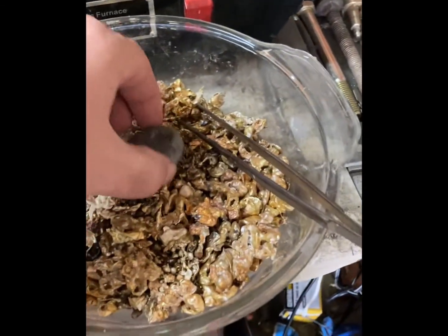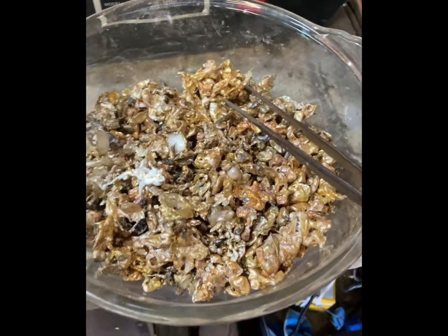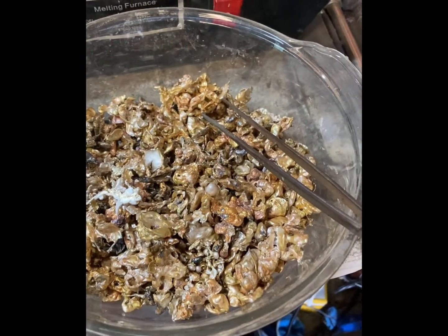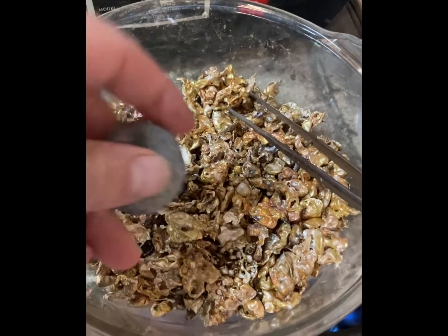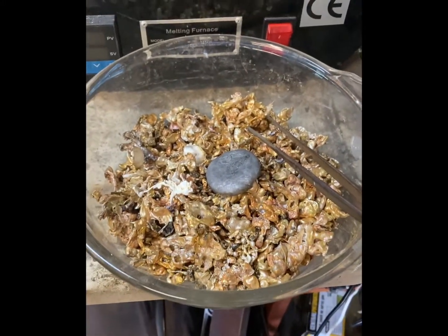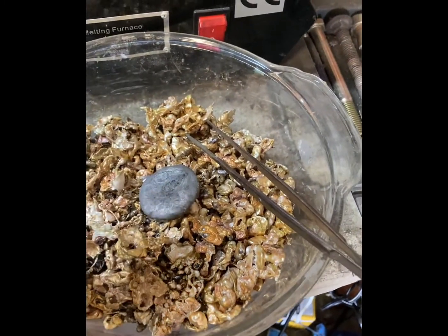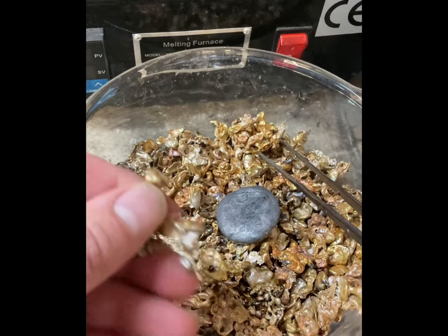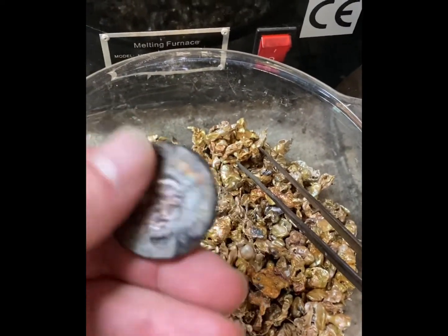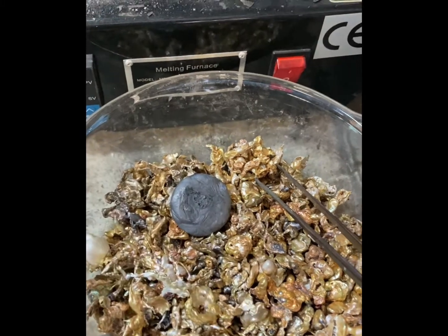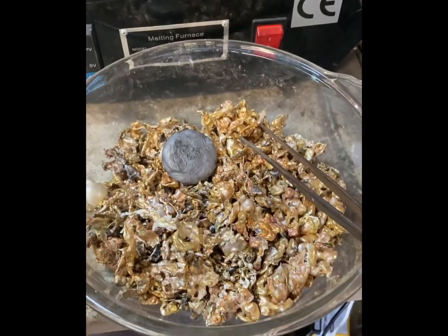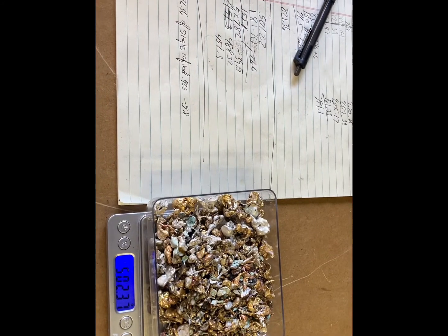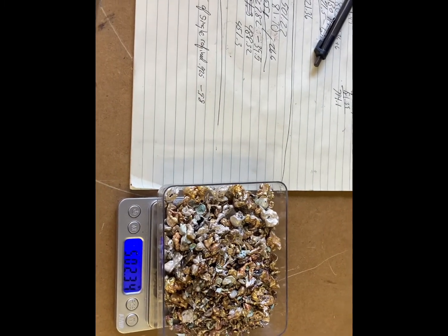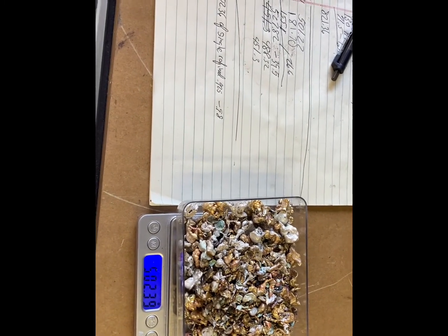Well, that's a bummer. I melted down about 800 grams of silver cement and contaminated it, either with the crucible or in the water I used for the shot. But you can see it's pretty contaminated. That was a pour and it looks terrible, so I'm gonna have to refine it again, so it'll be double refined. This is the second half of the double refined batch. I had 1,000 total grams of refined silver that got contaminated when I went to make it to shot. Got contaminated in a bad crucible, so I am refining it again.